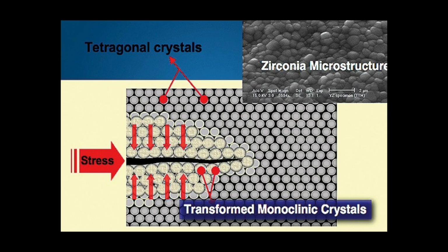Hypothetically, think that a crack forms and starts propagating. There will be highly localized stress concentration at the crack tip, and this stress will be sufficient to trigger grains of ceramic to transform from tetragonal to monoclinic, that is T to M transformation. This occurs in the vicinity of the crack tip.